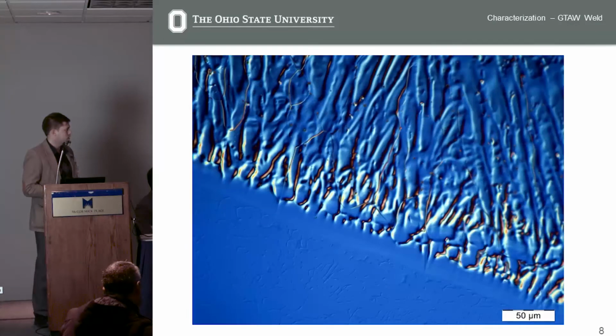This is the typical GTAW overlay weld that we see. The microstructure is much coarser due to a lower heat cycle, due to the higher heat input process. And also the planar growth region in this weld is just drastically larger than the one that we previously saw. It should be noted that the average dilution of the filler metal bead above the fusion boundary is about 25 to 30%. So this isn't exactly 52M sitting on top of this 304. It's somewhere in between 304L and 52M composition.